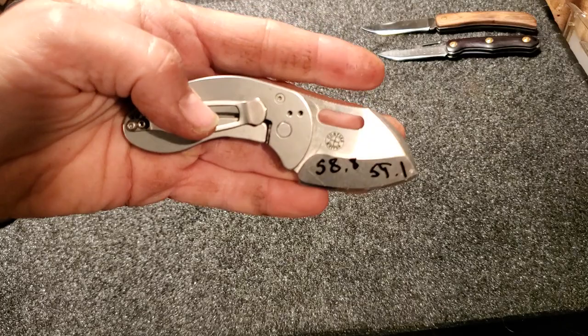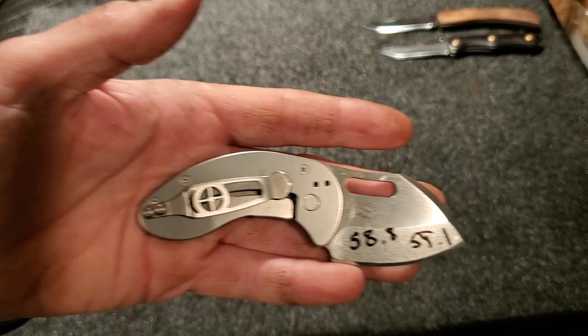A lot of people say they've never heard of this — it's a Curtis Design Boker knife in 440C. It came back at 58.8 and 59.1. My understanding is that 58 to 60 is good for 440C, so that should be a decent little performer.